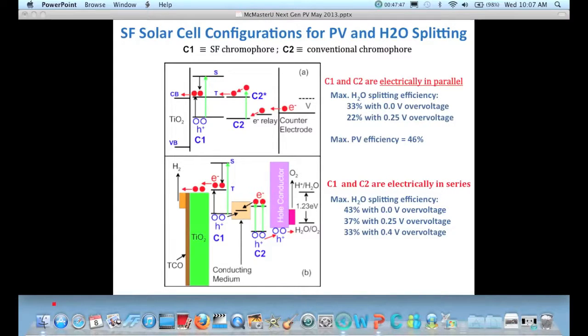You need to have a second absorber here to absorb the light that's not absorbed in the singlet fission chromophore, because the transition from the ground state S0 to the triplet is forbidden. The transition is from S0 to S1, so it allows smaller photon energies, less than that energy gap, to be transmitted. So you need to pick it up in the second absorber. And the efficiency for PV would be about 46%. What's interesting here is that it's like a tandem cell, but you don't have to match the photocurrents like you do in a normal tandem cell, which is shown here for water splitting. In a normal tandem cell, you've got to recombine a hole from one chromophore with an electron from the other to maintain charge neutrality, just like in a multi-junction solar cell.